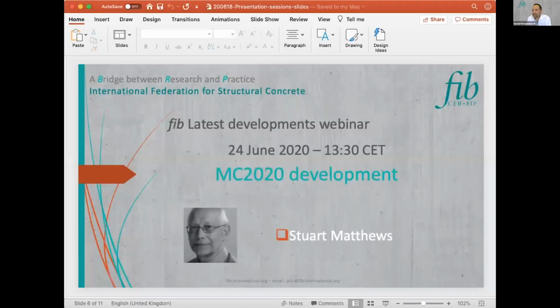One of the questions is from Vyacheslav Javakowski to Professor Matthews. What about the type of cement for the durable concrete with cement content less than 100 kilos per cubic meter? A lot of that comes from particle packing, but it's certainly been demonstrated by various colleagues in FIB and in universities that you can, I think Jos Walraven demonstrated an effective concrete mix with only 70 kgs of cement, but many of these developments have been achieved by optimizing the particle packing arrangements rather than using the cement as a filler.